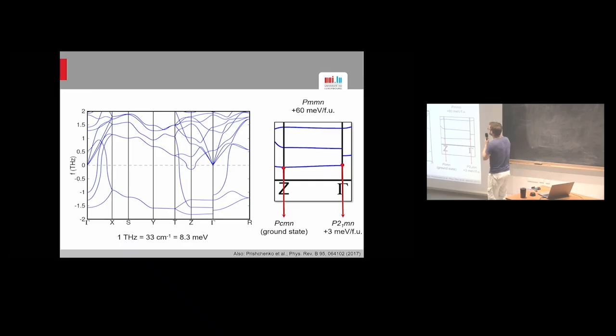Just to put some numbers in for those who want, the high symmetry phase has this particular symmetry. This is what you would get if you condense the polar mode, so if the phase is ferroelectric, and this is what you would get if you condense the antipolar mode. If this one wins, the ground state is technically this one, because it has lower energy, but then this one is like 3 meV per formula unit above, which is essentially degenerate. At the level of accuracy of DFT, it means nothing.